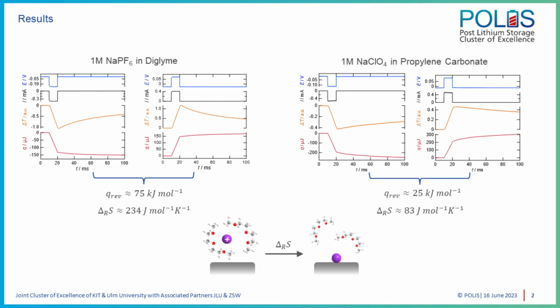And when we now consider the heat effects from ion transport during the reaction, these values of the reversible exchanged heat correspond to a change in the reaction entropy of 234 joule per mole Kelvin for sodium deposition in diglyme and 83 joule per mole Kelvin for the deposition process in propylene carbonate. So in both systems, the entropy change during the deposition process is strongly positive, which is not expected for the immobilization of the ions on an electrode surface. However, these results can be explained by the influence of the solvent molecules. In the solution, the solvent molecules form complexes with the sodium ions and are therefore fixed in the solvation shell of the ions. And during the deposition, the molecules are then released from this solvation shell and cause an increase in the entropy, which outweighs the entropy loss by the immobilization of the sodium ions on the electrode surface.